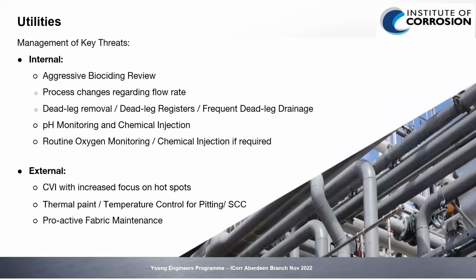So how do we plan to manage these? In addition to inspection techniques used here, RAD, we also plan to conduct a full chemical review, as stated by Lewis. This review will determine whether current biociding is sufficient and if pH levels have been maintained to prevent acid formation within the system. In addition to this review, we also recommend looking at process control, in particular flow rate. This, combined with an updated dead leg strategy, we feel will dramatically reduce the threat of MIC. For the heating and cooling regions, we suggest monitoring to determine whether oxygen is present. If high levels can be found, then this should be part of the wider chemical review.